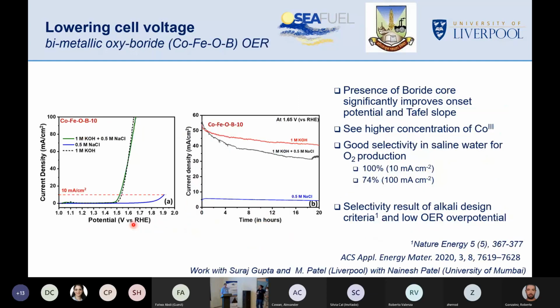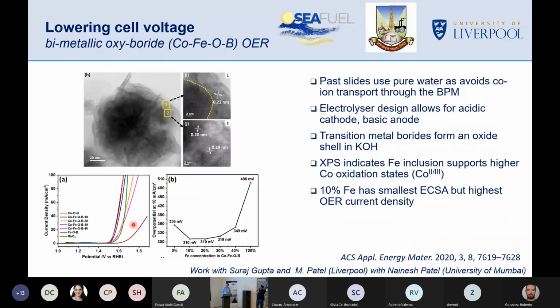Back to what the active site is. We can see a clear correlation between the onset potential and minimizing the overpotentials for 10 milliamps per square centimeter for the formation of the cobalt 2, cobalt 3 oxidation pre-peak. So clearly it appears to be that cobalt site, exactly the same as you see in a cobalt oxide catalyst.